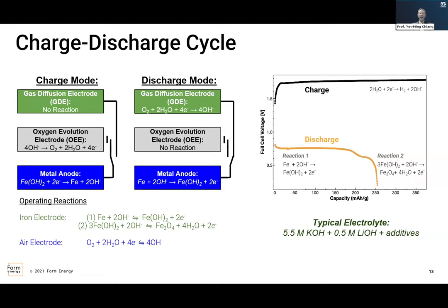The right-hand side shows you that by electrochemical terms, this type of battery is actually much less efficient than a lithium ion battery. If you look at the voltage gap between the charge discharge curve, as well as the capacity gap between the charge and discharge curve, you see that there is both a Faradaic inefficiency and a voltage inefficiency. Together, the round trip efficiency is on the order of only about 50%. Okay? So much worse than a lithium ion battery.